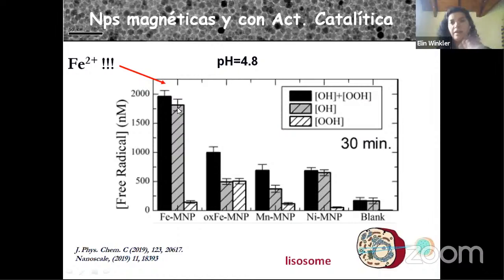So here is the result, and I'm just finishing. We observe that in magnetite, where iron 2+ is present, here is the quantification. We use a standard so we can know the concentration of free radicals. When we have iron 2+, the system presents a very large concentration of free radicals. This is important, that we have this large amount at pH 4.8. And when we change the pH to 7, we do not observe the generation of free radicals. In the other cases, the production of free radicals drops. The oxidized nanoparticle also presents a very low concentration.